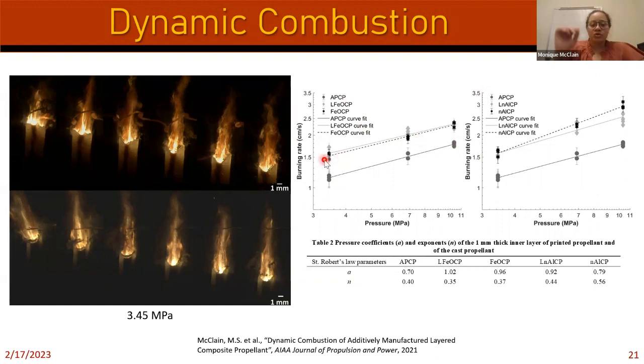And then we compare those two. We look at that iron oxide layer and the normal single iron oxide material, and we found that those burning rate slopes were pretty much the same. So if we compare those here, I have the N, and we look at the burning rate of that inner layer compared to the burning rate of that material by itself, pretty much the same. No real difference there. So that was good.